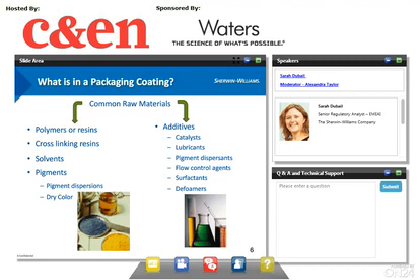So it contains several raw materials. The coating is a layer of organic material applied to any substrate for the purpose of protection, fabrication, and/or decoration. Main ingredients are the resins, either main resins or cross-linking resins. They provide most of the coating properties such as corrosion resistance, flexibility, hardness. And the choice of a resin is a series of formulation compromises, balancing chemical resistance and flexibility. The resin influences the regulatory status of the final coating. And usually the main resin gives its name to the coating, like epoxy, polyester, acrylic, phenolic, vinylic.